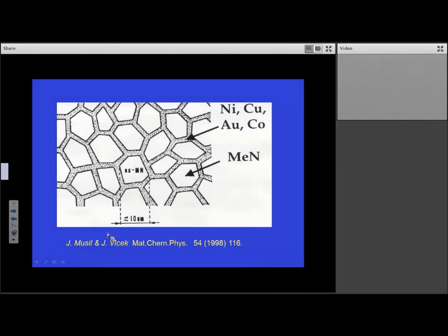One of the earliest proponents of nanocomposite coatings was Jindřich Musil in the Czech Republic. He originally said that the idea would be to have a metal nitride in, for example, an amorphous soft metal grain boundary phase. Our approach is to go slightly further than this. What we're looking at is nitrogen or boron interstitially hardened metal crystallites within a soft metal matrix to try to retain that metallic characteristic in terms of ensuring a low modulus phase, but still getting a hardened effect due to the interstitial hardening within the grain.